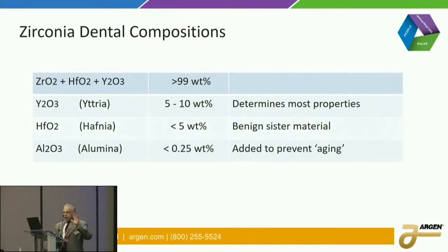Now, there are some companies that jumped on the bandwagon very fast, and some companies that held back. The reason they held back is because of this problem here. If you take the alumina out, you risk the structural integrity of the material, and no one really knew how that was going to happen because this product was not developed for the dental marketplace initially. So some companies held back until we understood how this alumina content could be reduced without disturbing the aging problem. And nowadays we have materials like our HT Plus, for example, that has less than 0.1% alumina, and it's very nice and translucent.